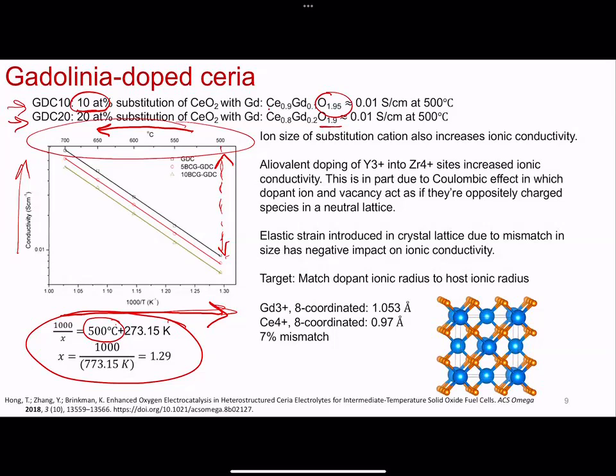So GDC, people have looked at it because obviously higher ionic conductivity, but why? So here, you start out with cerium dioxide, CeO2. So cerium is now in the 4+ state because oxygen is in the 2- state, but you have 2 of it. So that's 4-, and so cerium has to be +4. If you replace with gadolinium, that's a 3+. And if you look at the ionic radii, it's a much closer match than yttria and zirconia. So yttria and zirconia, that's about 17% ionic mismatch. Here it's 7%, so there's a little bit less strain in the material.